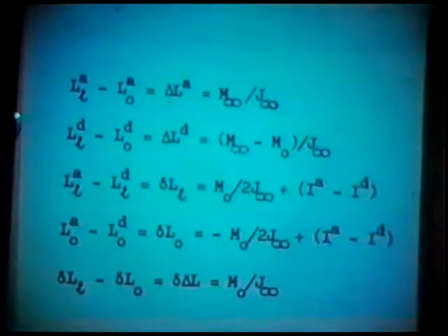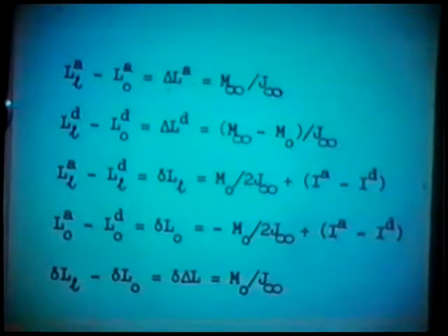But if we could have that slide again, you'll notice that these integrals are not involved, and in the last line you have a means of finding from flow experiments the value of, if you measure the final flow and you measure the 4 time lags, you can find this delta L. Therefore you can find the equilibrium uptake in the membrane.